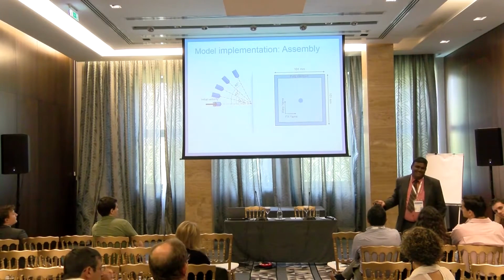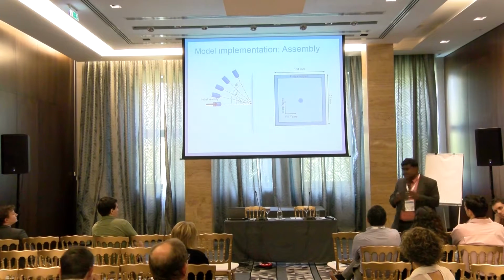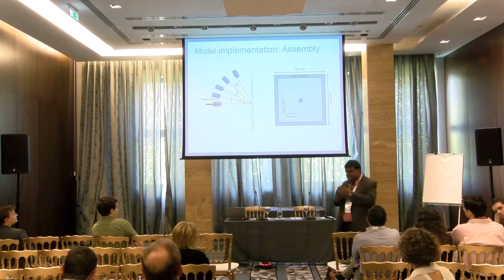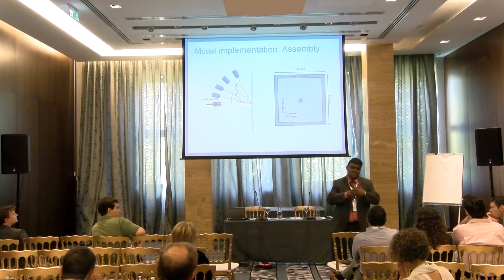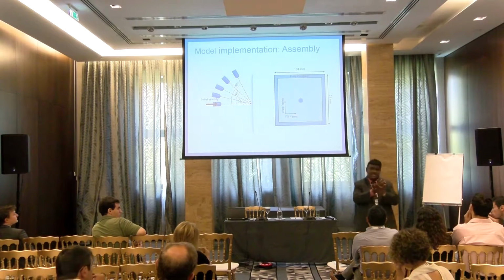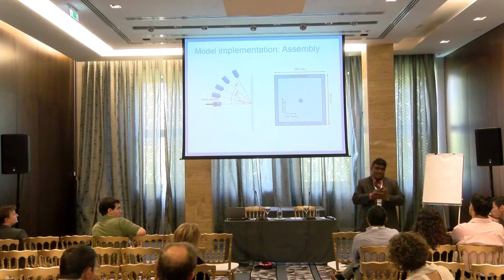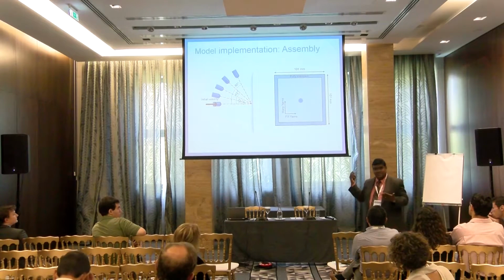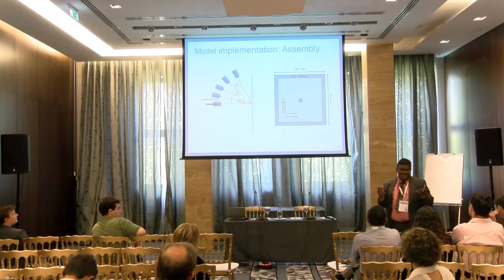So why do you need to use cohesive elements at the interface? If you use a matrix, and you have the warp and fill fibers joined together with the matrix, so you have an interfiber strength. Now we have friction, so fibers can slide and we have friction dissipation. Although we can incorporate the friction force on the fiber, which adds another one-dimensional force like a shear force on the top and bottom of the fiber itself. And if you have a matrix, you have to have cohesive behavior.